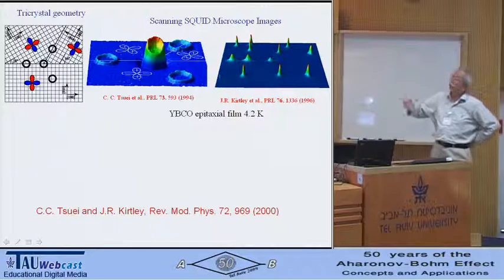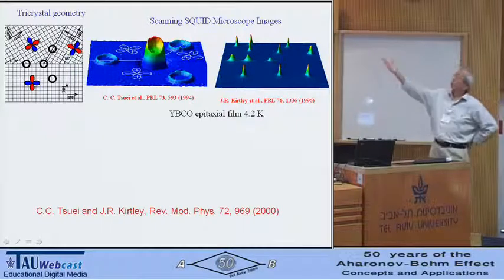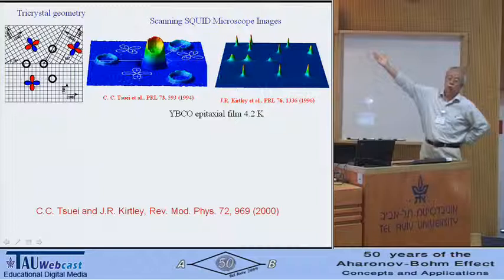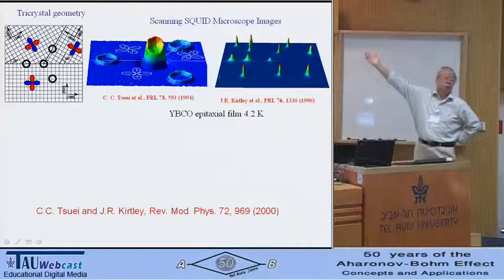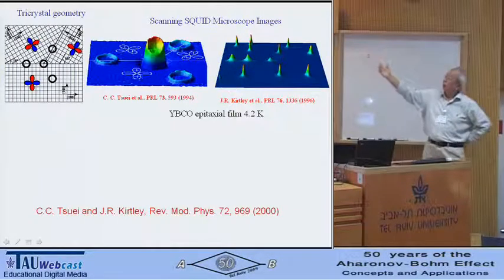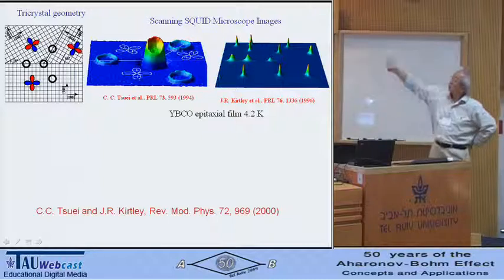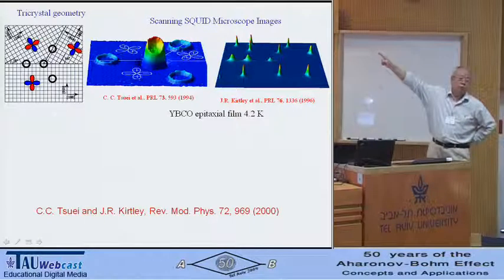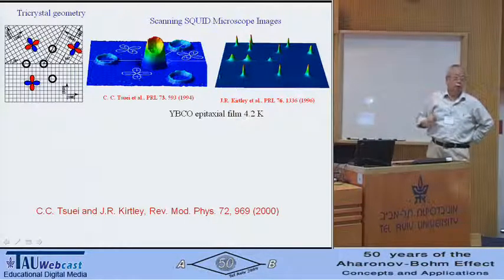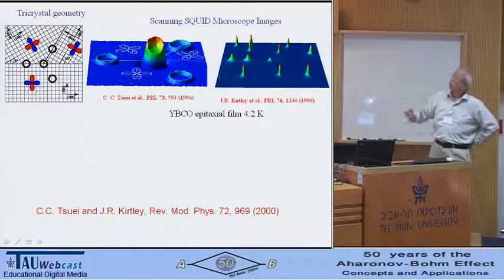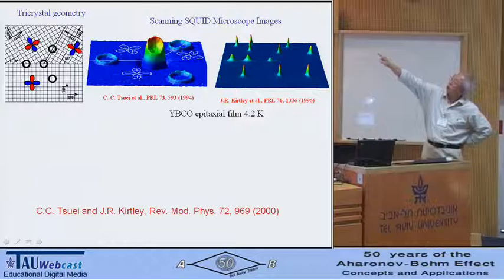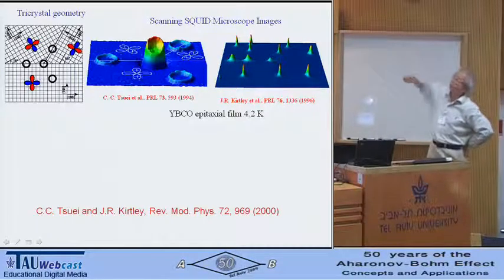Now what you do is you just deposit film, and using a scanning SQUID microscope, look at the vortex. And you see at the center, there's a small vortex in there. That's a half flux quantum at the tricrystal. That's where it's supposed to be, if it's a d-wave. And then you see the Josephson vortex along the boundaries. See, it outlines the boundary like this and that.